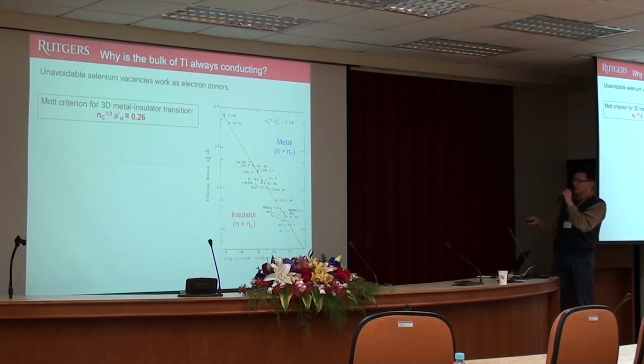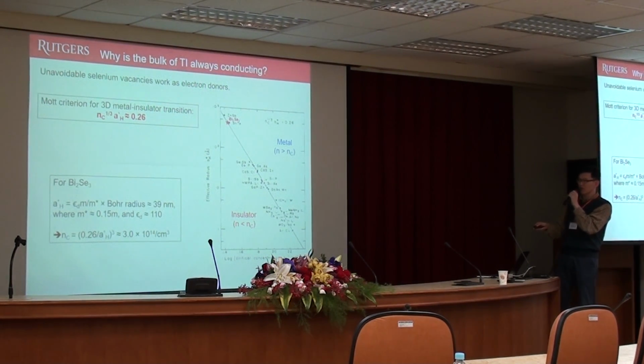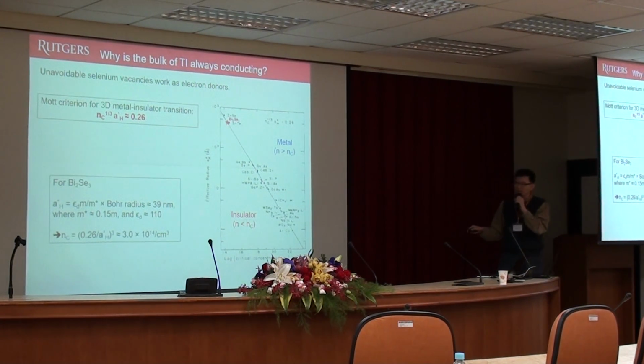If you did that kind of very simple calculation for bismuth selenide, it turns out that if you plug in the dielectric constant and effective mass, this critical carrier density is something like 10 to the 14 per cubic centimeter, which is 4 orders of magnitude lower than that of silicon. It's right over here. So what does this mean? It means that your defect density should be lower than 10 to the 14 to have this bismuth selenide system in an insulating state in the bulk. Otherwise, if your defect density is larger than 10 to the 14, then they will remain metallic.